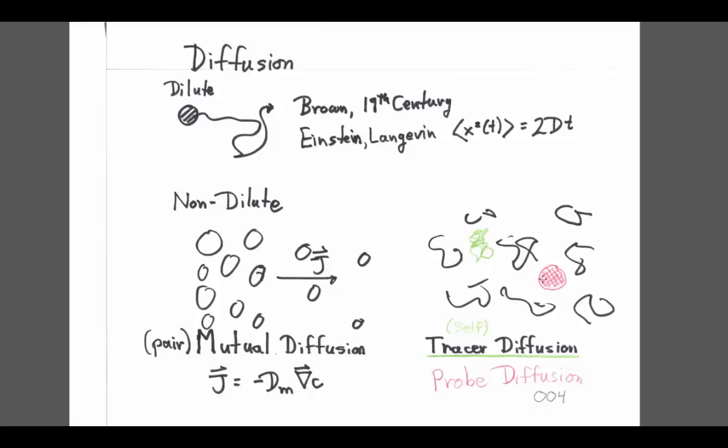I will note that when I came onto the scene in 1969, the image that was used for diffusion was always the Langevin diffusion. The number that you measured with the diffusion measurement was called the diffusion constant, at least in light scattering circles. Some chemists knew better. And there was no recognition that there were two different diffusion coefficients, let alone that it was intelligent to ask which diffusion coefficient light scattering spectroscopy measures. The answer is indubitably that light scattering spectroscopy measures the mutual diffusion coefficient in a binary system.